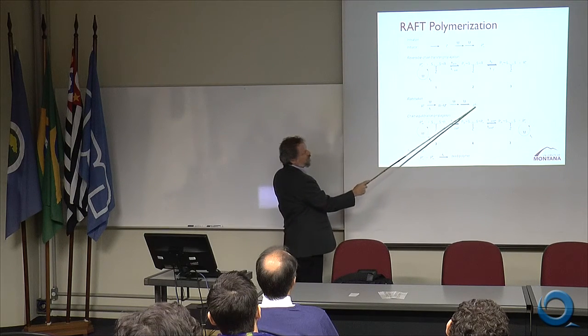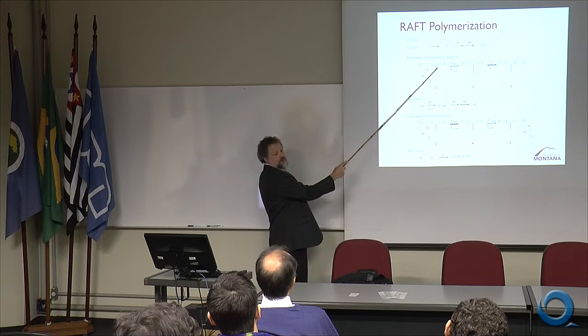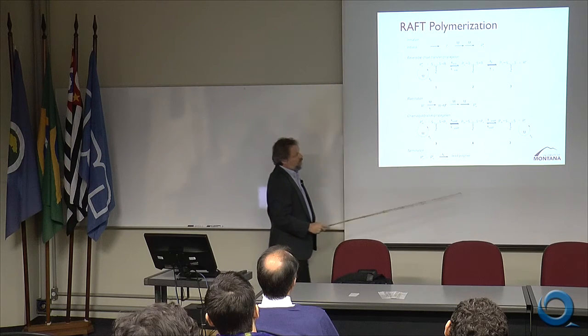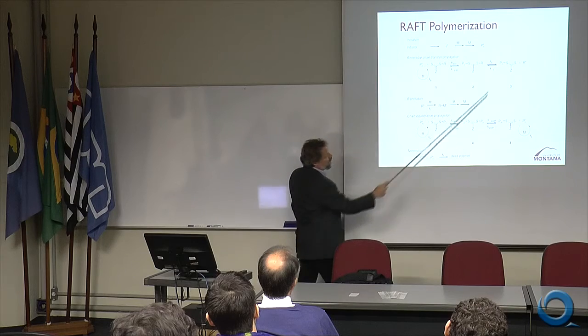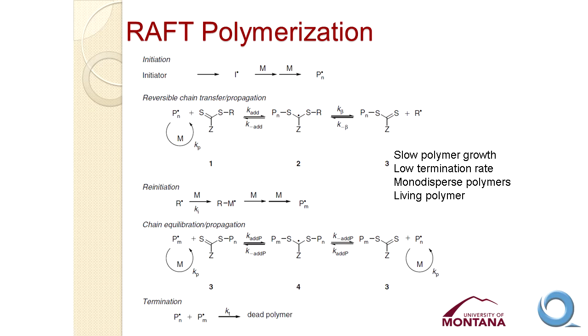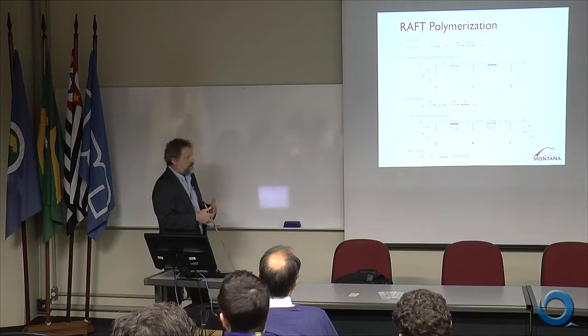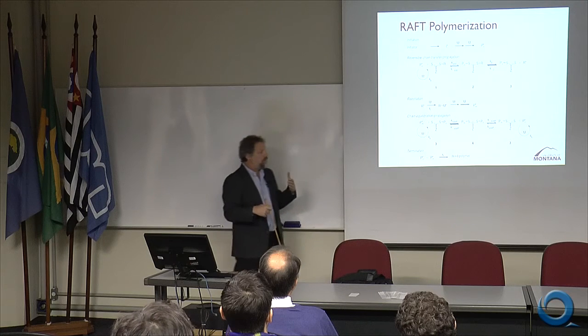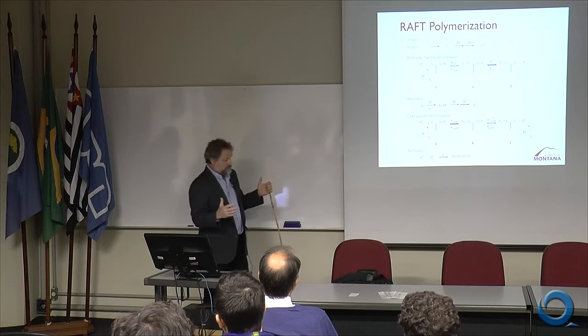And what that means is that the number of growing chains is nearly equal to the number of chain transfer agents. So most of the growing chains in this system are actually in this form, where the growing polymer chain is capped on the end by the chain transfer agent. And then we have a small concentration of growing polymer chains in solution, which will react with the chain transfer agent, form this intermediate, and displace the other chain, which starts to grow. This process goes back and forth, allowing each of these chains to grow at about the same rate. And so over time, we have these polymer chains growing much more slowly than in an uncontrolled free radical polymerization, and forming relatively monodispersed polymers, which do not have a great deal of range in molecular weight.